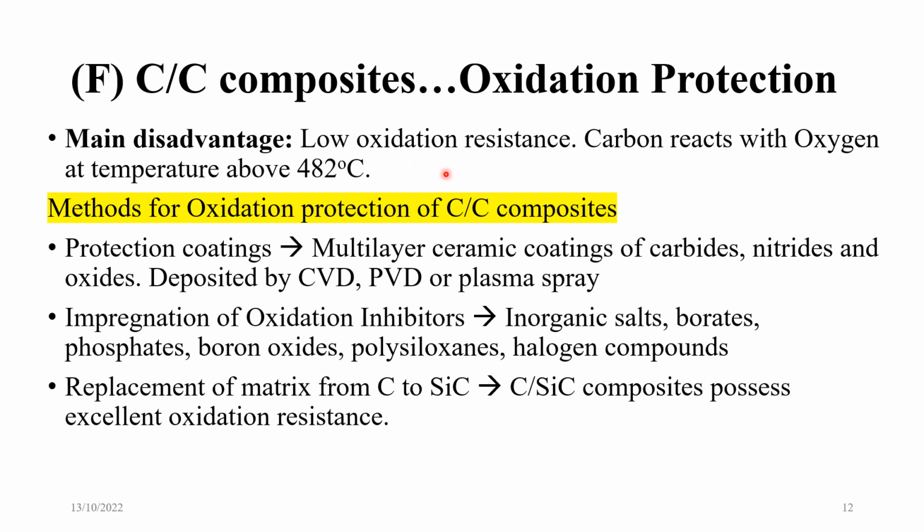The disadvantage is low oxidation resistance. So that one has to work on. Carbon reacts with oxygen at a temperature of 482 degrees Celsius. See, it's a very low temperature. Compared to the performance of the carbon, this temperature is quite low.